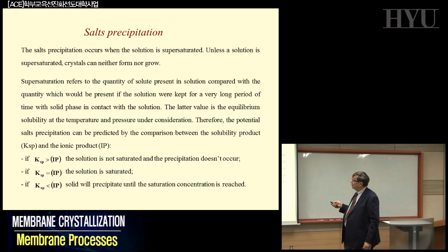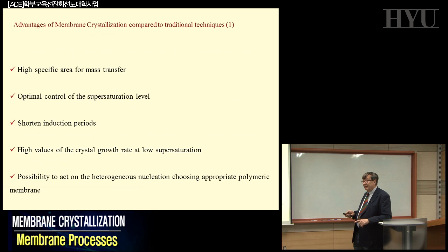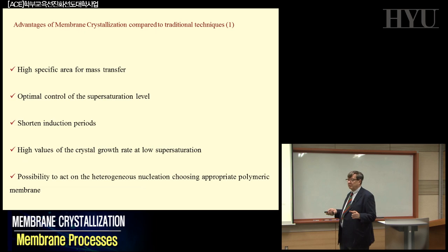So the first thing you have to learn a lot about is salt precipitation and all this story about the solubility of the different salts, when they don't precipitate, when they precipitate, when they overcome the supersaturated solution that will be formed, etc. The other thing that you have to learn is that when you precipitate something, I was mentioning epsomite, they assume only magnesium is coming down. Not at all. If you have any strontium present, even at very low concentration, 10 ppm or 50 ppm, during the formation of the epsomite, you can have entrapment of the other bivalent ion, can be barium, can be strontium, and this will change significantly the crystallization story.